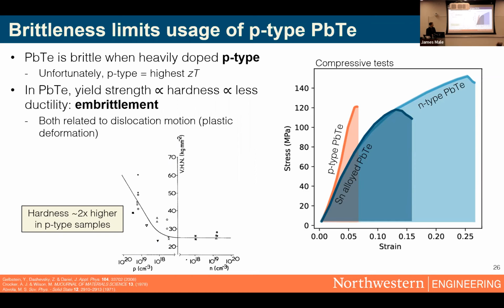But more often people do hardness measurements. In this case, hardness is actually a pretty good proxy of yield strength. And they often find that the hardness is far, far higher when you dope the material P-type as opposed to N-type. So essentially, high hardness here corresponds to the high yield strength of P-type lead telluride. Those 2 things might sound like good properties. However, we see from these experiments that high yield strength leads to lower ductility. So in this case, we actually want to reduce hardness to make a tougher sample, or use other toughening mechanisms, but that hasn't really been explored yet.